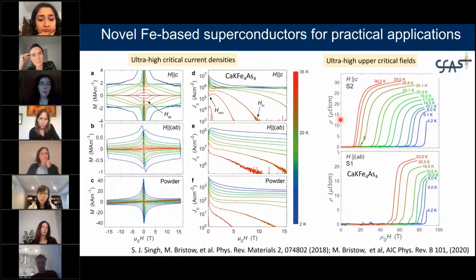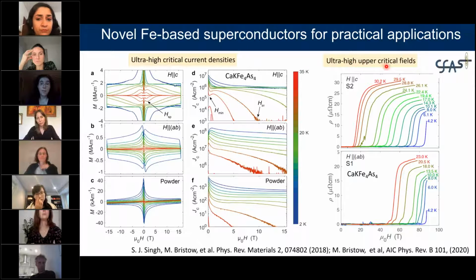And thinking about application, in our group we also explore the properties of materials which are relevant for practical application. We found that this calcium potassium iron arsenide four four has extremely large critical current densities and high upper critical fields close to 100 Tesla, and critical currents, some of the largest reported for an iron-based superconductor, which makes them potential for practical applications. These are determined from magnetization measurements, and the upper critical field from transport studies.